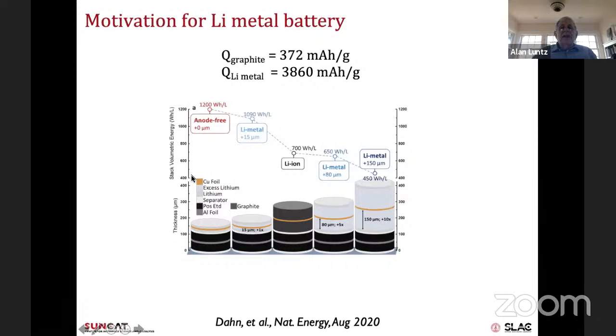So if you look at the volumetric energy density you expect for a conventional, state-of-the-art lithium-ion, it looks something like this here. As I will explain in a minute, when you use lithium metal, you have a real problem about consuming active lithium in the cycle. In a discharge charge cycle, you consume some of the active lithium, you have a very low coulombic efficiency. So one way around that is just to add a lot of extra lithium. The problem with that is then you don't get the advantages of this high capacity battery to give you a higher volumetric energy density. So you can have just a little bit of extra lithium than you're using in the discharge charge, but then that's very hard to deal with.